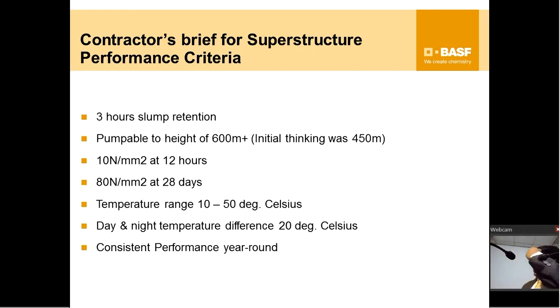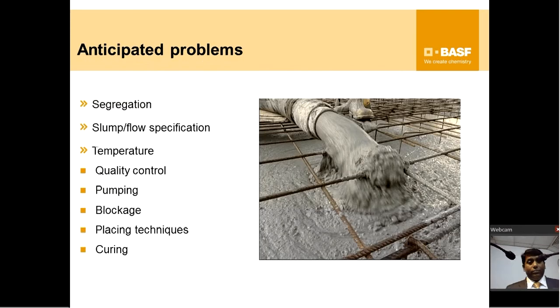80 newtons at 28 days, with temperature ranging from 10 to 50 degrees. So you need the admixture to work, be compatible, and give you workable retention when the temperature is down at 10 degrees, as well as in the simmering heat at 50 degrees. The day-night temperature difference is sometimes as high as 20 degrees, which is very difficult to manage on a single day. Consistent performance year round is needed. What were the anticipated problems? Segregation, slump flow specification, temperature control, quality control, pumping, blockages, placing techniques, curing. All these were concerns.